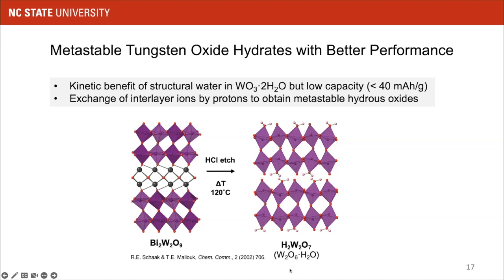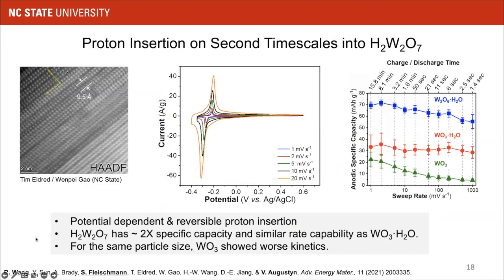The interesting thing is that now this material shows a much more potential-dependent response for proton insertion, whereas before we had this much broader response. We have a very specific potential dependence in the cyclic voltammogram.